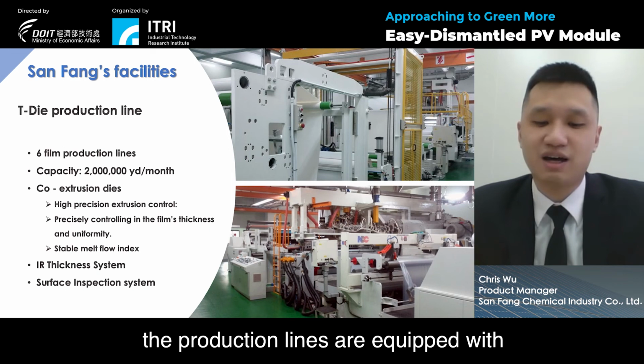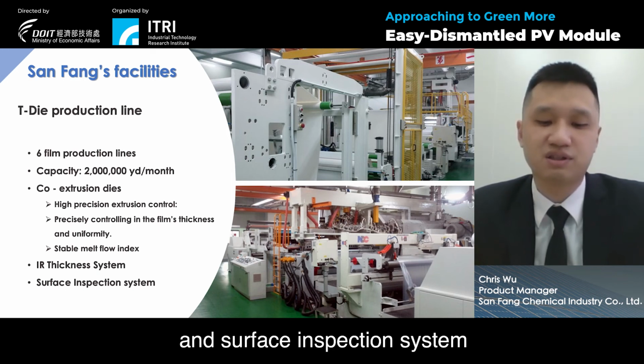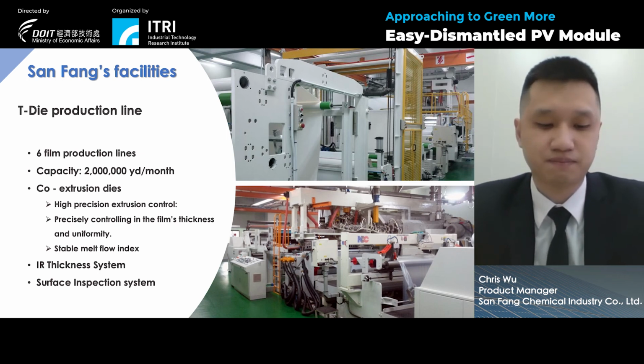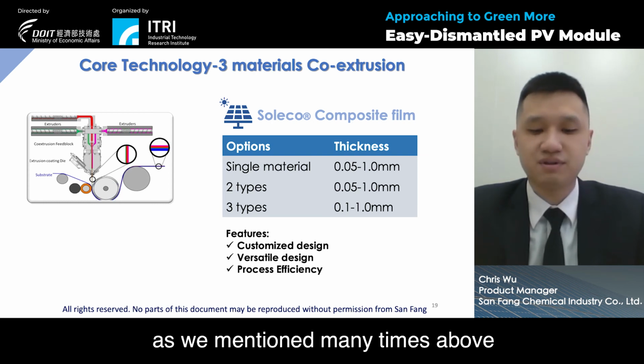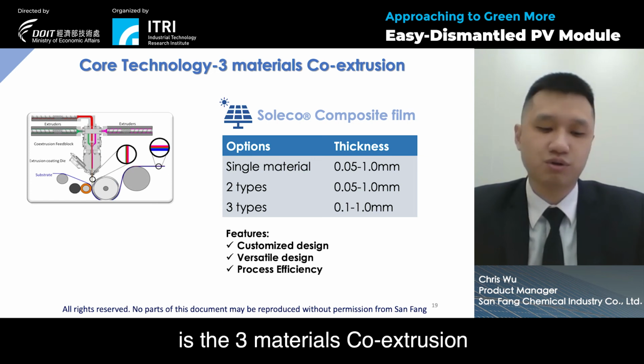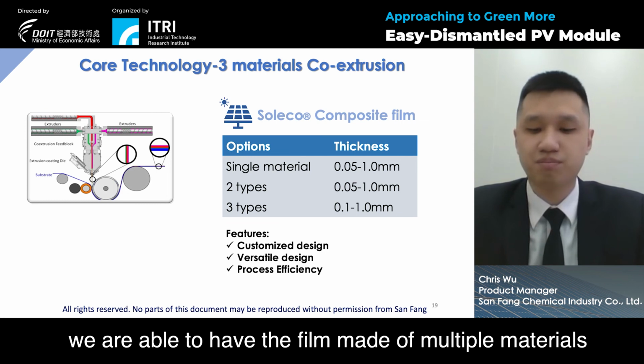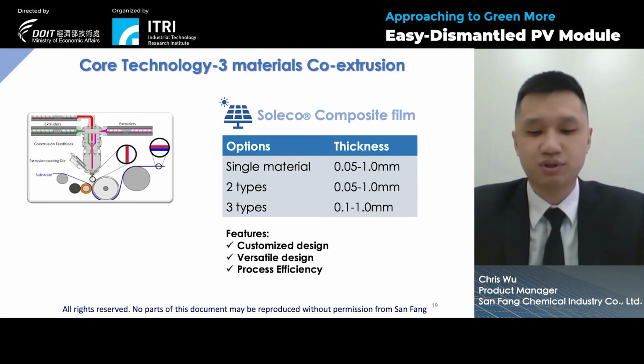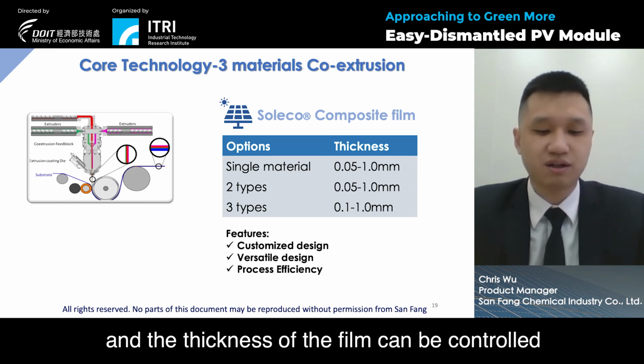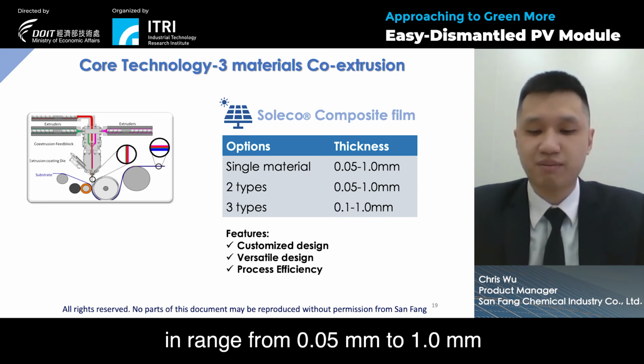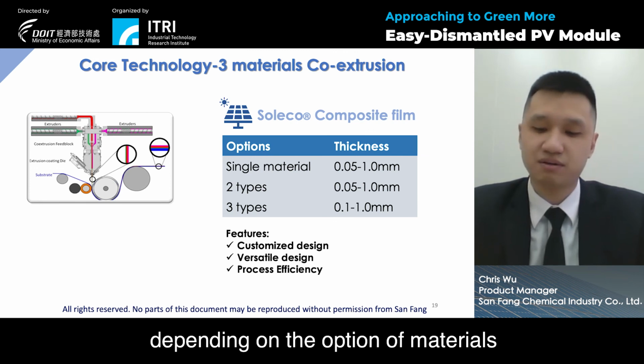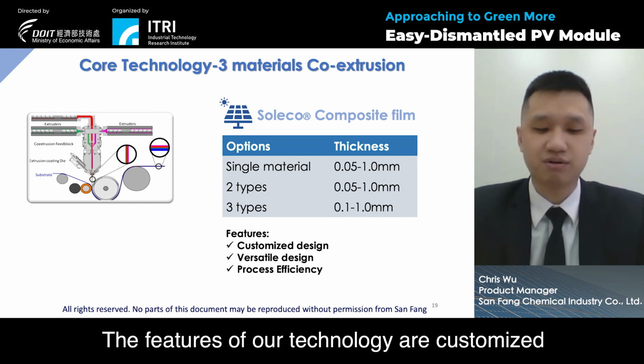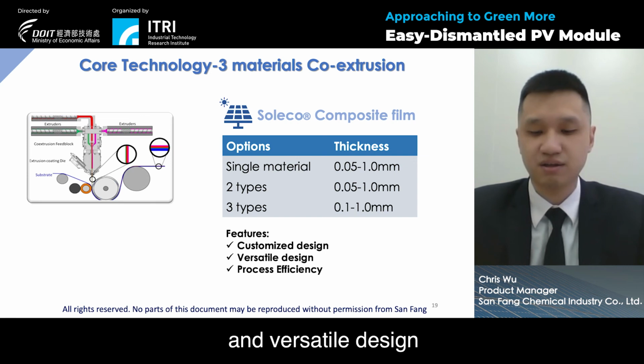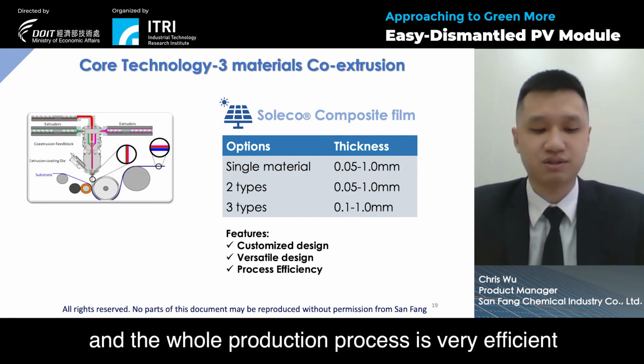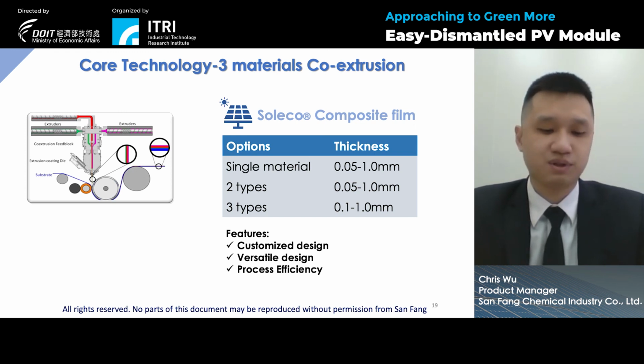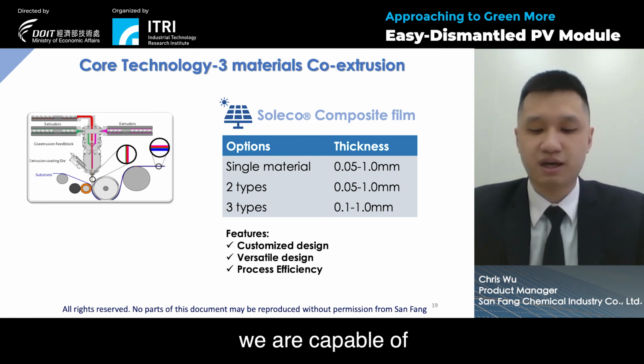Furthermore, the production lines are equipped with a thickness monitoring system and a surface inspection system to ensure the quality of the products. Finally, as we mentioned many times above, San Fang's core technology is the 3-material co-extrusion. We are able to make a film from multiple materials. The option is from 1 up to 3, which we can mix to fulfill customers' needs. The thickness of the film can be controlled in a range from 0.05 millimeter to 1.0 millimeter, depending on the choice of materials. The features of our technology are customized and versatile design, and the whole production process is very efficient. We can do it all at one time. With San Fang's technology, we are capable of making your innovative design happen.